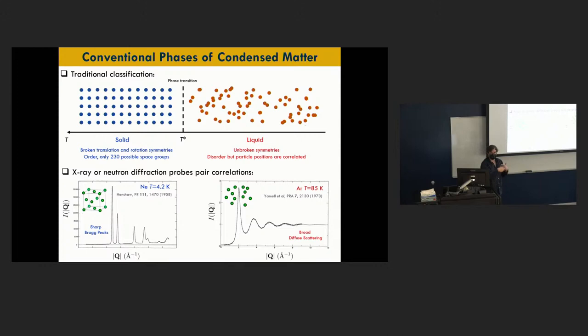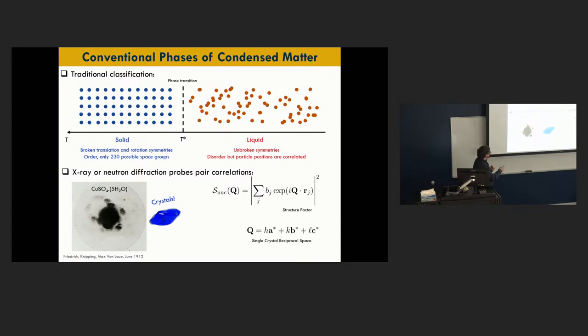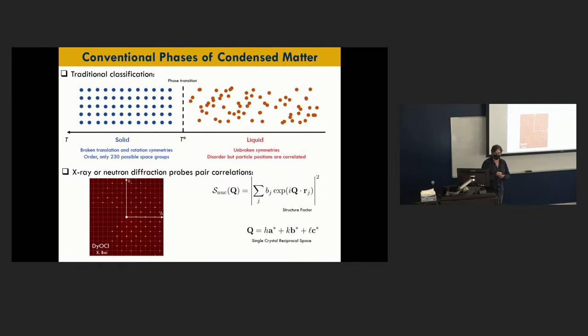So in my research, we essentially do the same, except we use magnetic materials that are liquid in the sense that their spins are not ordered. And instead of using X-rays, we use neutrons to characterize such correlations in matter. Okay? Of course, you can also do this on crystals, and these are some nice 1912 measurements, and this is a nowadays measurement on some crystals, so there's been a lot of progress in X-ray diffraction.